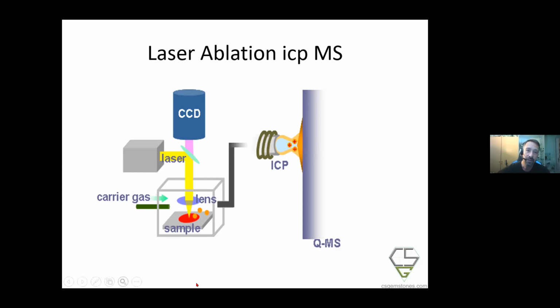So this material that has been removed from the gem will be carried with a carrier gas into an ICP-MS, inductively coupled plasma. What happens here, we disintegrate all these parcels of material that are coming through, and we create ions. So we create ions out of everything, and these ions are then analyzed in a mass spectrometer. Mass spectrometers are machines that separate ions by the mass over charge ratio, and they can count the number. So what you get is how many ions of what kind are in your sample. Sounds pretty easy, perfectly easy. In fact, it's a little bit tricky.